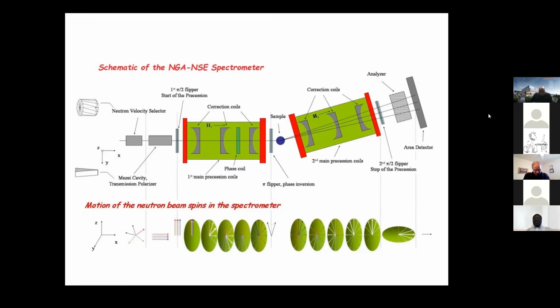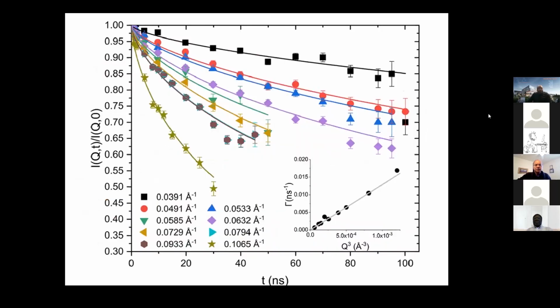It points in a direction. So we polarize the neutrons, tip them, and put them through a magnetic field in the first green arm on the left, and it precesses like a clock, and that's how we keep time. It scatters from the sample, and it goes either faster or slower through that second arm, depending on if it gained or lost energy. We just look at the time difference between the first leg and the second leg, or how many times it's precessed, and that gives us information on the energy exchange. In particular, we measure a time correlation function.